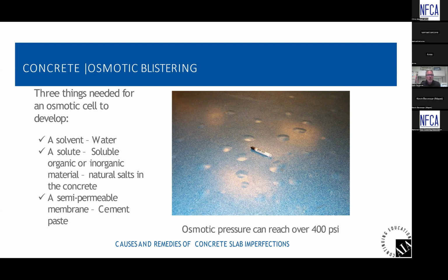Osmotic blisters. Maybe you guys have heard this term before. It does not happen very often. And there are several things here, three things actually, that need to happen for an osmotic blister to occur. Sometimes you see osmotic blisters in polymer coatings, even in epoxy terrazzo, epoxy coatings. And for this to happen, number one, we need a solvent, and certainly in applications of concrete, that solvent could be water, could be groundwater as the source, possibly could be mixed water if we haven't let the concrete dry enough. We need a solute, and that's basically a soluble organic or inorganic material.